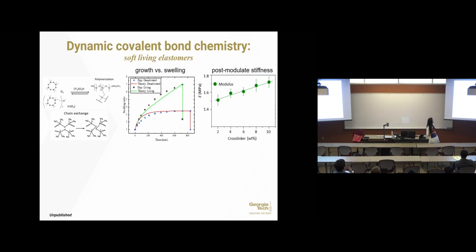This is a monomer, and in the presence of acid or base solution, which works as a catalyst, this ring will open up and connect together to form the network. And as long as your catalyst, this acid or base, is active, this dynamic network constantly exchanges with neighbors to homogenize the stress. So that will allow us to do this growing.